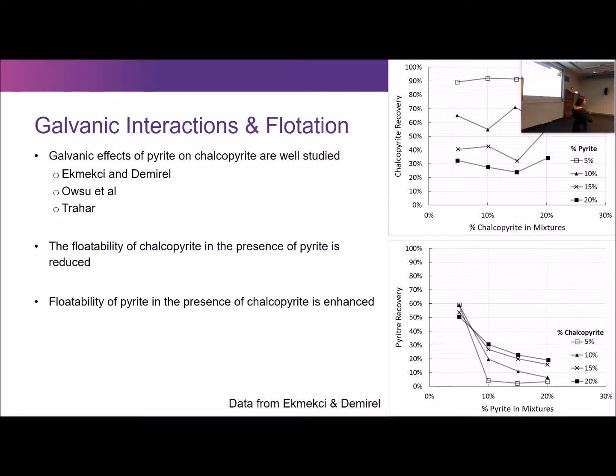And ultimately what happens is when you've got chalcopyrite present on its own, or in the presence of small quantities of pyrite, it floats beautifully. Chalcopyrite floats like crazy. But as soon as you start to add more pyrite to the system, the floatability of chalcopyrite drops off the wall. It prevents chalcopyrite from floating by merely being present. On the other hand, if you have pyrite floating in the presence of chalcopyrite, initially the floatability is relatively good, but then when you have more chalcopyrite in the system, the flotation in fact gets better. So when you have chalcopyrite floating beautifully on its own and pyrite floating poorly on its own, you mix them together, suddenly pyrite floats and chalcopyrite doesn't. Not what you want when you're trying to reject the pyrite.